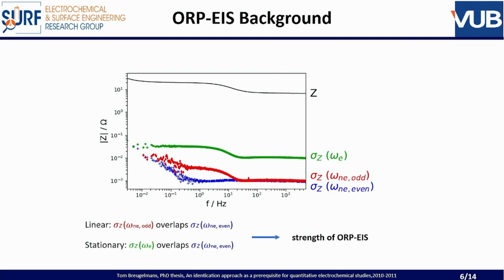But keep in mind that we also handle the time domain. This is very important because the high frequencies and the low frequencies are sampled in the same time domain, while in conventional impedance there is a history, because you usually sample from the high frequencies to the low frequencies, so you don't handle the time domain. We handle the time domain. In addition, as I showed you, we have access to the non-linearities and the non-stationarities. This is the extra information.